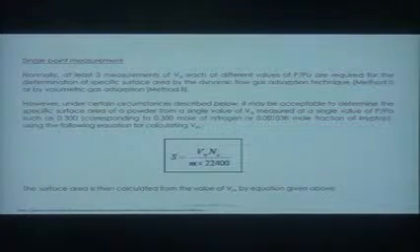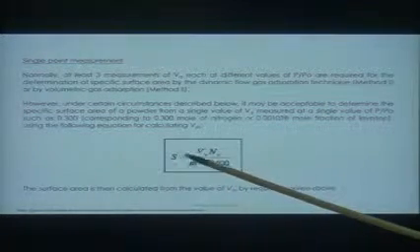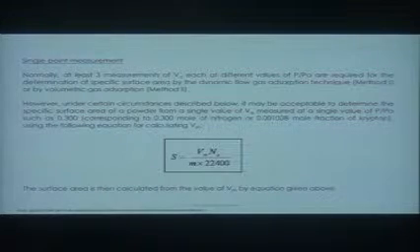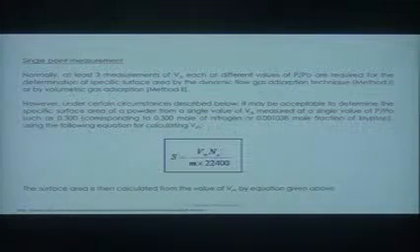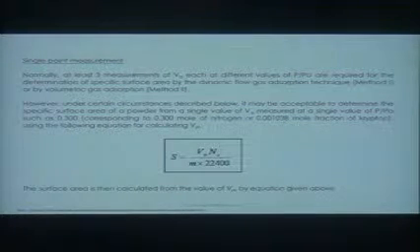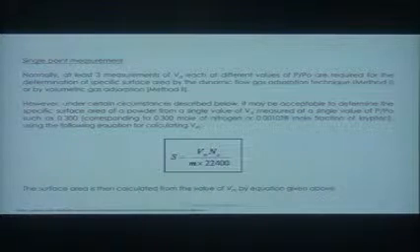If you do a point measurement, what we're after here typically is the surface area. So what you would do is you would try to measure this volume Vm, okay? Once you have that, and using Na as Avogadro's number, you can calculate the surface area. So Vm comes from the previous page. It can be extracted from the adsorption isotherms. I won't go through the theory, but it's a pretty straightforward method.